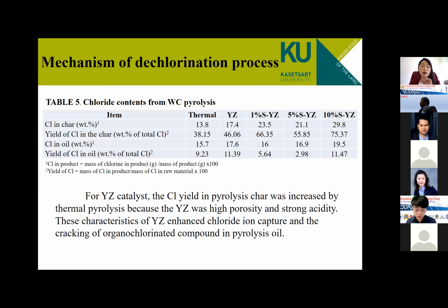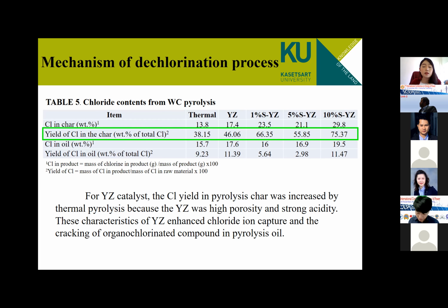Mechanism of the dechlorination process. For the YZ catalyst, the chlorine yield in pyrolysis char was increased compared to thermal pyrolysis because the YZ has high porosity and strong acidity. These characteristics of YZ enhance chloride ion capture and the cracking of organochlorinated compounds in pyrolysis oil.